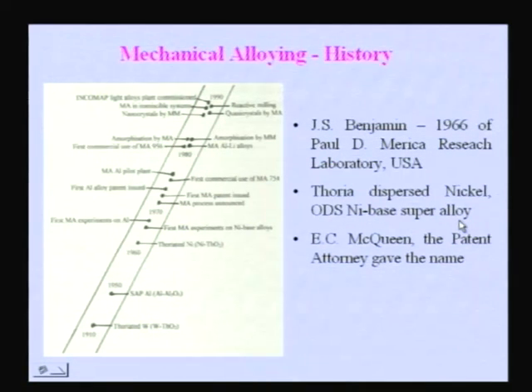That means instead of first coating the compound with the pure metal such as nickel and then putting it into a melt of nickel based superalloy, which is a two-step process, what they decided is to take all the elements which are required for the nickel based superalloy, put all of them into the ball mill, and along with that put all the oxide powders, so that you ball mill all of them together. When you ball mill all of them together, you can end up ultimately with a superalloy containing these fine dispersoids, and that gives you very high strength.